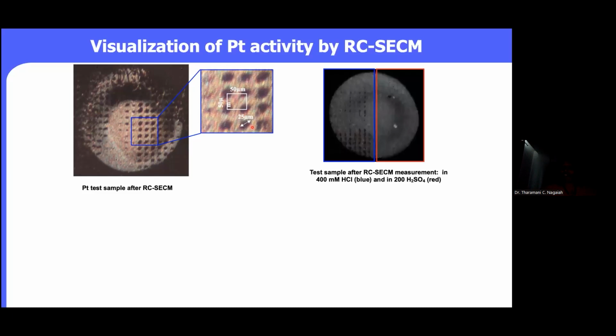But to confirm whether our speculation is due to the platinum dissolution or not, we have done some control experiments in the absence of chloride, that means in sulfuric acid. As you can see on the right hand side, we do not see the etching of the surface or the dots on the surface.